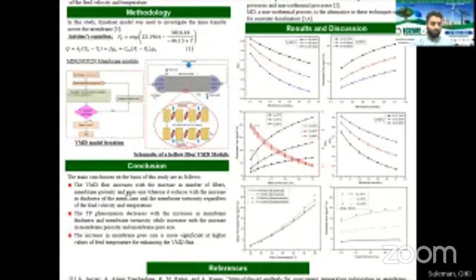And the conclusion. These are the main conclusions drawn from this study: the VMD flux increases with the increase in number of fibers, membrane porosity, and pore size, whereas it reduces with the increase in thickness of the membrane and membrane tortuosity, regardless of the feed velocity and temperature.